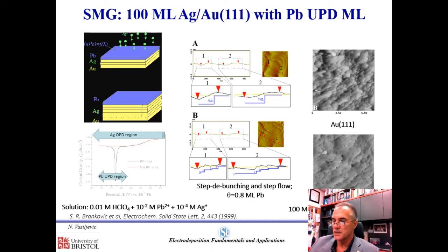So you can see here two sweeps for the solutions with lead and without lead ions, and with silver ions present, and you can see that this peak here represents the lead UPD on the growing silver surface. So when we have about 0.8 monolayers of lead on the growing silver surface serving as a surfactant, what we can actually achieve is that the rough starting gold surface looking like this can end up being covered with a silver film that is much smoother than the starting surface.